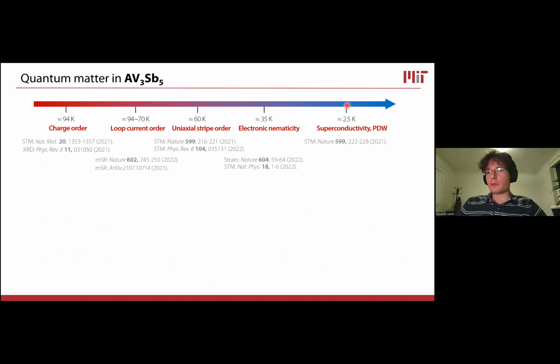So again, making a long story short, I don't really have time to give you the full summary about these materials. I think there are some few hundreds of papers that came out in the last couple of years. There's been a flurry of experimental and theoretical research activity on these systems. So the various forms of symmetry breaking that occur in these systems are a cascade of different transitions that starts with charge order at 94 Kelvin. Then you have loop current order, which has been detected with muon spin rotation, that happens between 94 and 70 Kelvin. Uniaxial stripe order, so breaking of rotational symmetry as well, happening around 60 Kelvin, particularly from NMR measurements. And then a form of electronic nematicity, which was seen with STM and NMR, that occurs at around 35 Kelvin, and then at last superconductivity and potentially pair density waves at very low temperature, around 2.5 Kelvin.